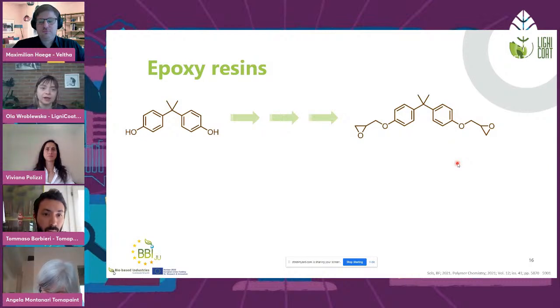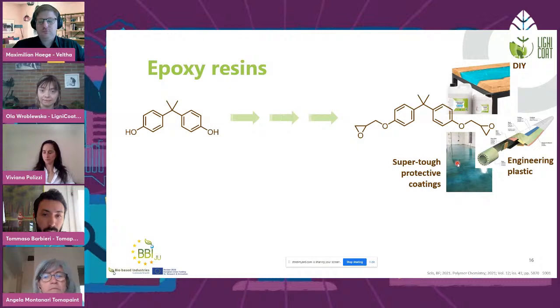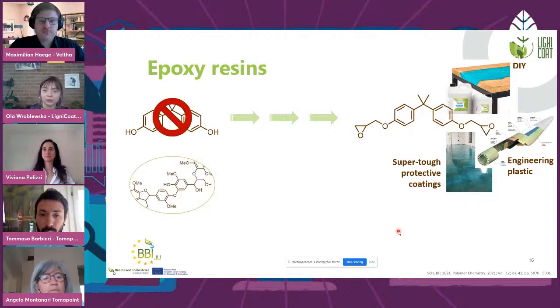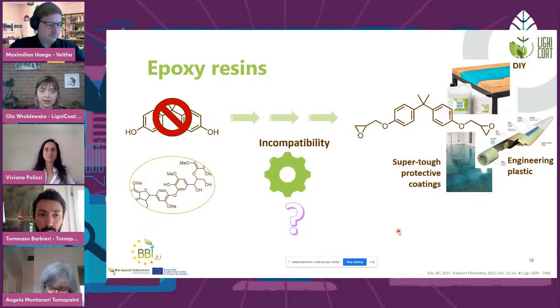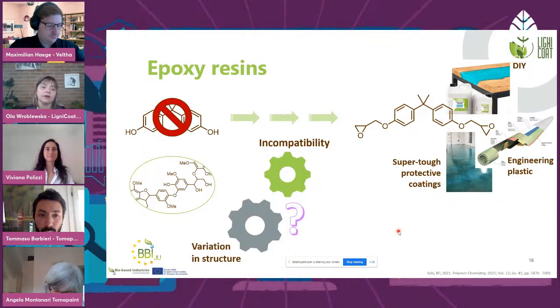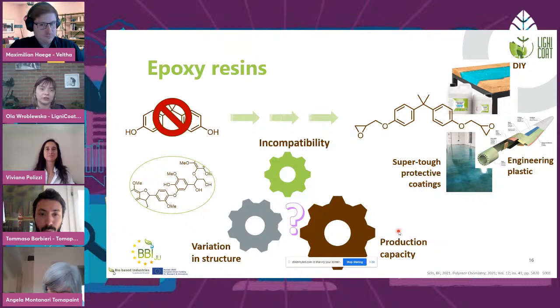And typical epoxy resins are synthesized from bisphenol A by a reaction which is called epoxidation. And you can find these epoxy resins in applications like DIY videos on the internet. It's very often used, but also in engineering plastics or super tough protective coatings. And in LIGNICOAT, we want to replace bisphenol A with lignin, and more specifically with depolymerized lignin. However, as it is always with innovations, there are certain challenges that we need to overcome in order to reach our targets. And these are incompatibility of lignin, a variation in lignin structure, and also production capacity.